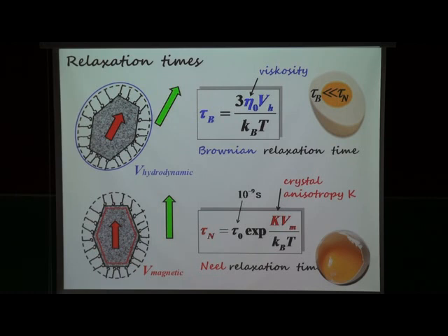But if you are working with magnetite, you are either in this part here, or you are somewhere in the soft egg regime. That depends on the size of your diameter. And then remember that if you have a size distribution, some particles will be raw eggs, and actually it's most of them, the small particles, and only a few large particles will be hard-boiled eggs. So this makes the situation quite complicated.